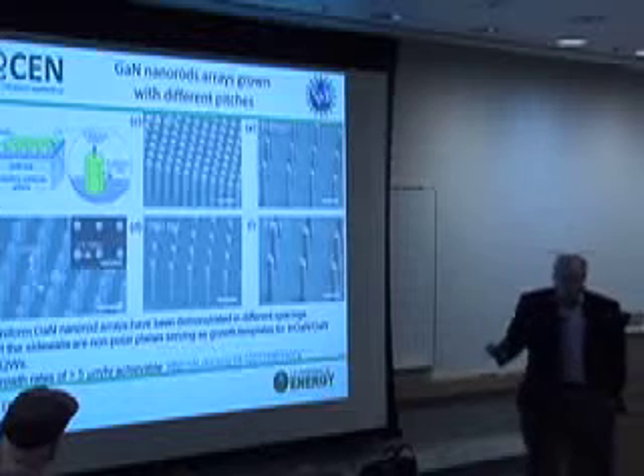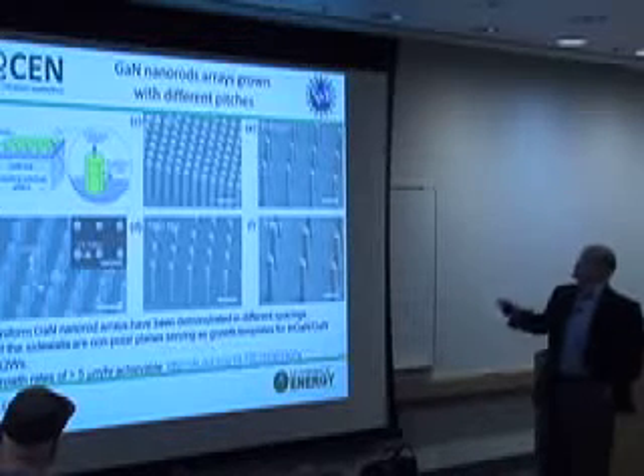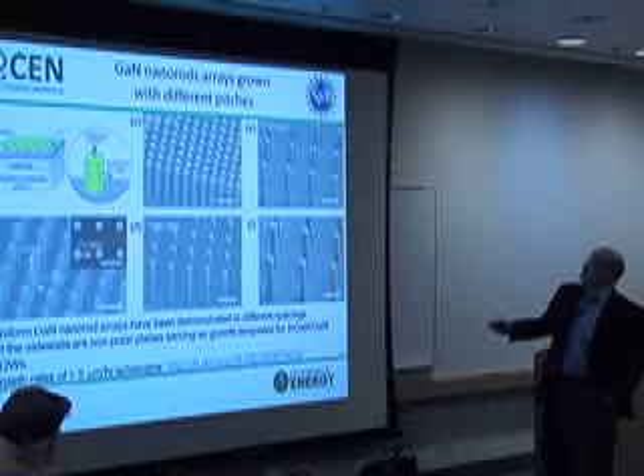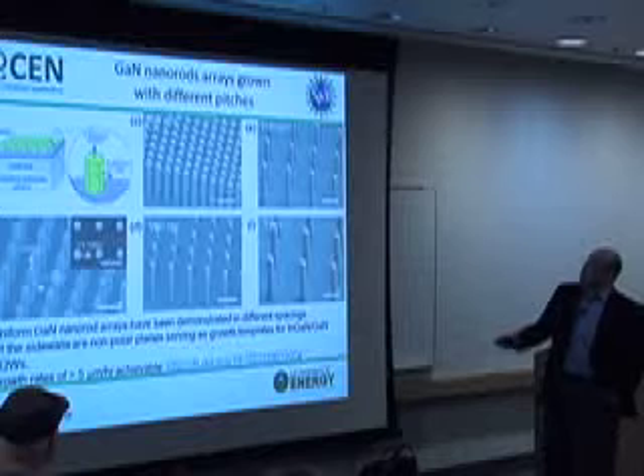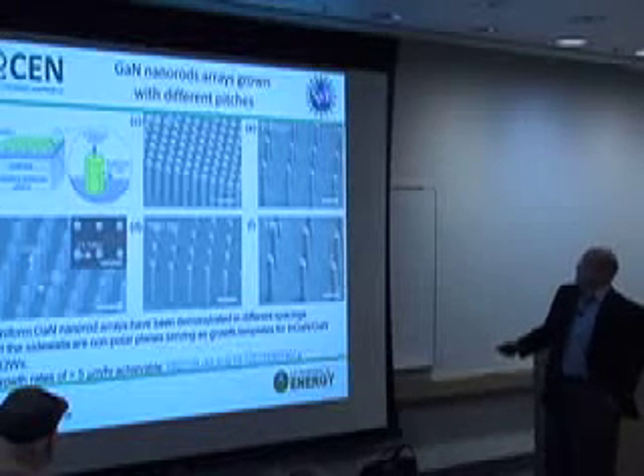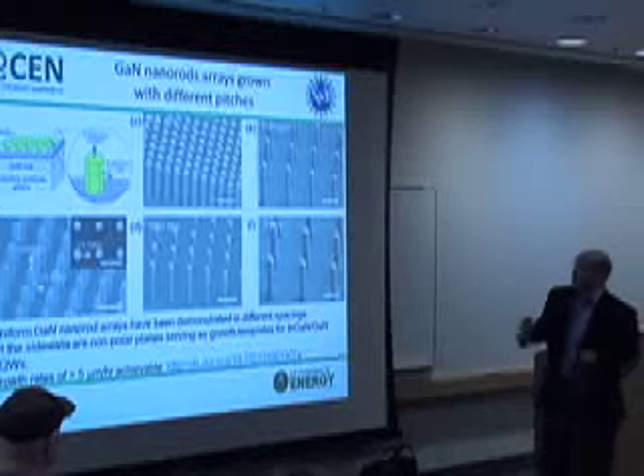So we've devised 2 or 3 different growth regimes in order to do that. This just shows some examples to convince you that we can do it, on different center-to-center spacings and with different openings in the rod. And in all these cases, you find that the surfaces are M-plane surfaces.